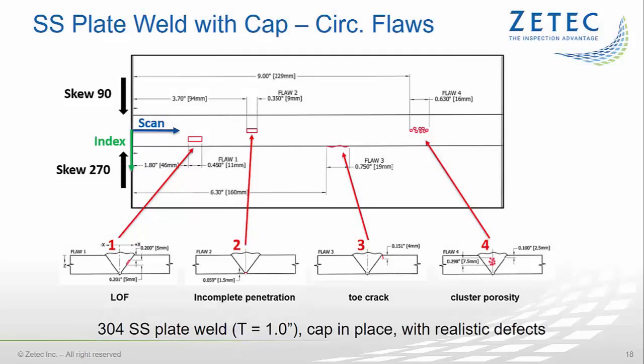The first test specimen is a 304 stainless steel plate weld with a wall thickness of 1 inch. The weld has a typical V-bevel and an as-welded surface condition. It contains 4 realistic and well-documented welding defects oriented parallel to the weld: a lack of fusion, an incomplete penetration, a toe crack, and a cluster of porosities.